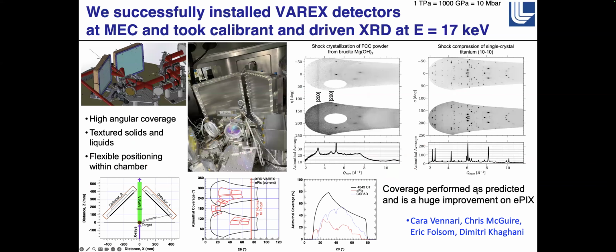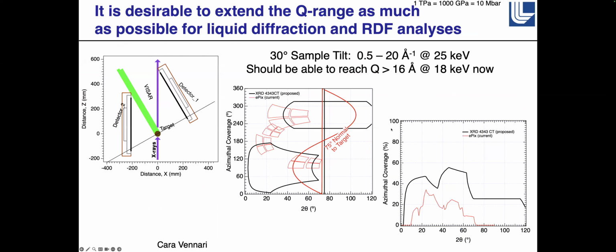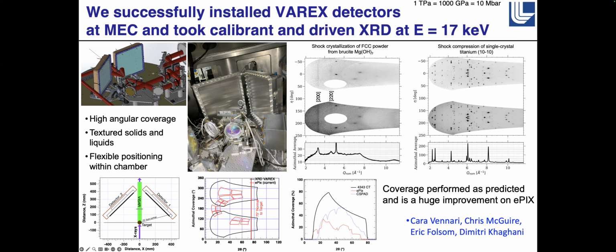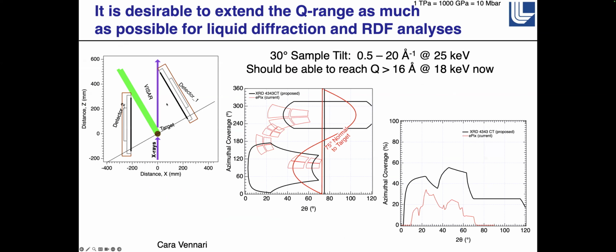So we've purchased big detectors that we're installing at LCLS. We've done one run with them, and we're going to do another one in February. This shows the quality of the data that we got from it, which is very good. We designed these so that they can be placed anywhere within the chamber. We can put them in this configuration, which will get us out to 20 inverse angstroms at 25 keV, and we can operate at 18 keV now at LCLS, which should get us out to 16 inverse angstroms. There's a typo there.